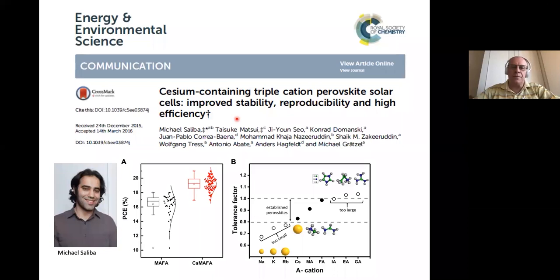But moreover, if you compare here, this is the triple cation with hundreds of cells measured. And if you take then the average or the spread, it's a narrower spread than the double cation. So we put our neck out here and said that the triple cation, besides increasing the efficiency, also improves reproducibility. When the reviewer came back to us to say, well, if you say that, let's prove it. And the question was if there was more than one person in our lab who can do this. These cells are actually made by 3-4 people as a team effort to show that there's not only one champion in the lab, so to speak.